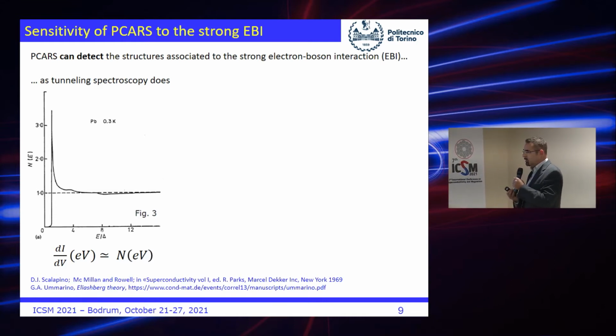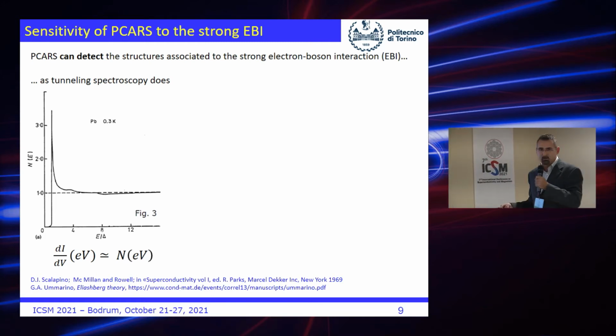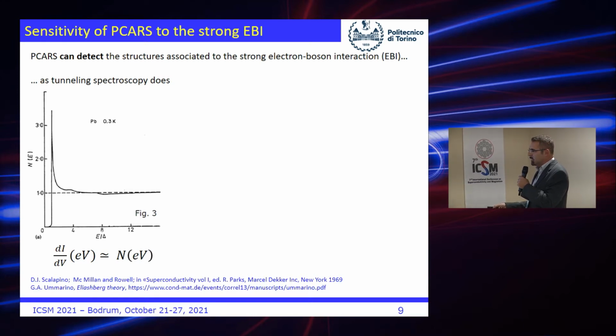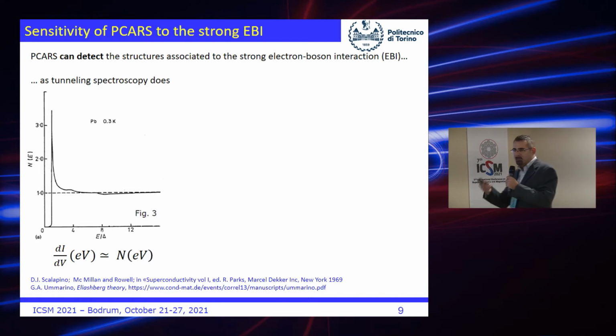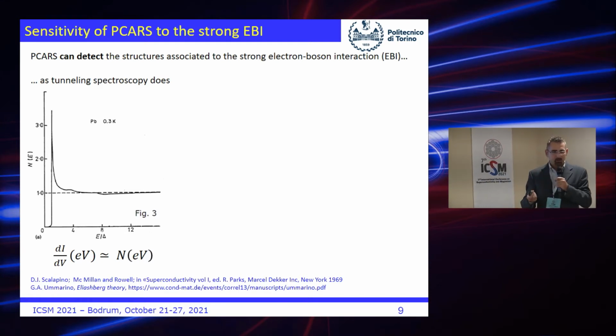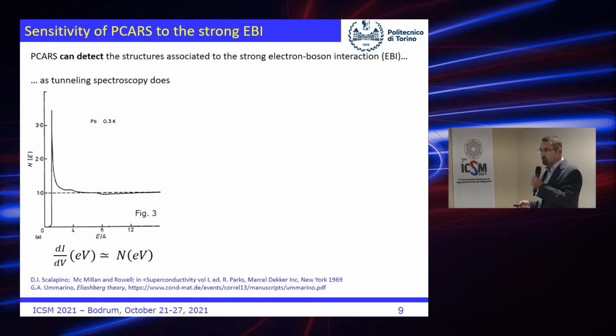Now, we know that in tunneling spectroscopy it is possible to see the footprint of the strong electron-boson coupling. In the case of lead, the boson is actually a phonon. This is the tunneling density of states, and you see that it deviates with respect to BCS because there are some wiggles. These wiggles are produced by the alpha squared F, so by the Eliashberg function of the boson. In this case it's a phonon.